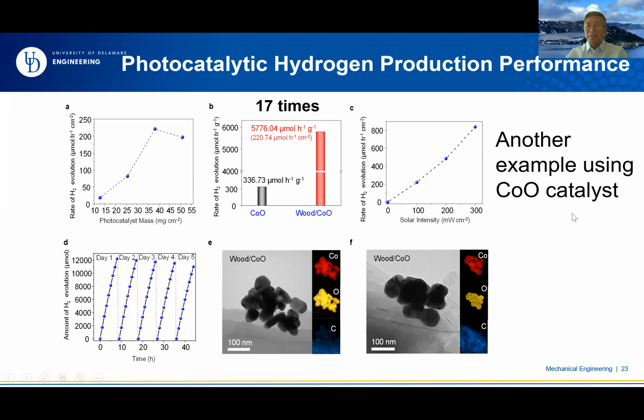And let me give you another example, by using cobalt oxide catalyst here. Again, of course, you need to figure out what might be the optimal catalytic loading. In this case, we found that about 38 milligram per centimeter square achieved the best performance for hydrogen production. Again, compared to the triphase case, the hydrogen production increased by 17 times.